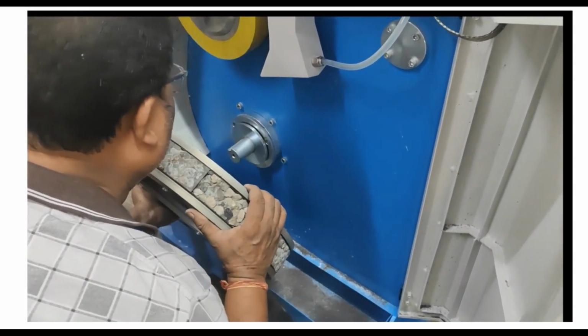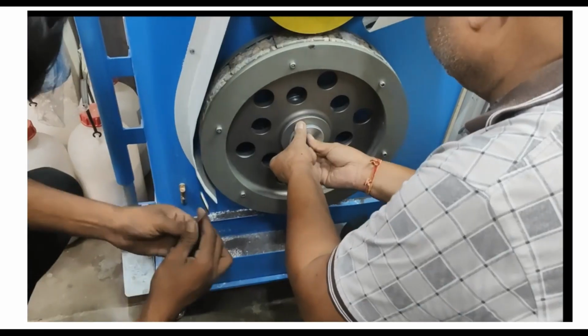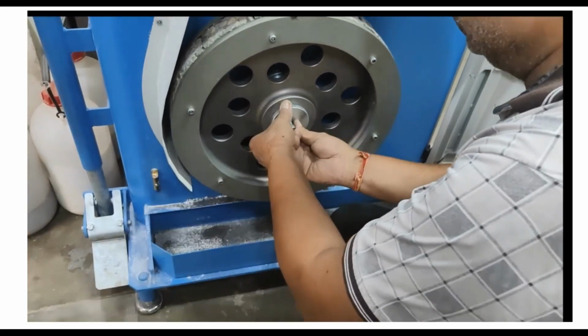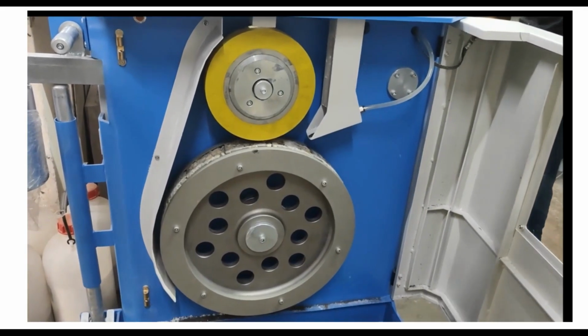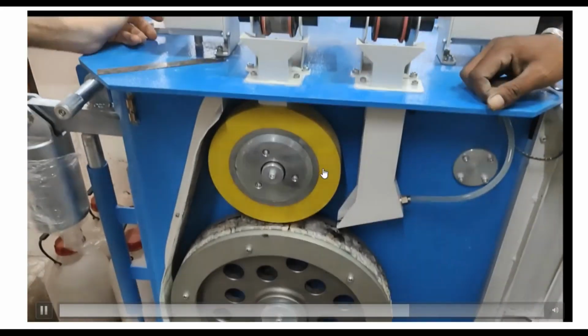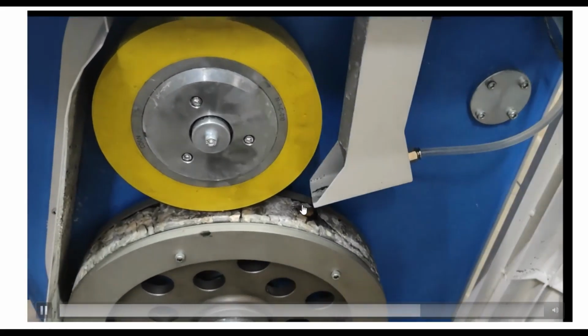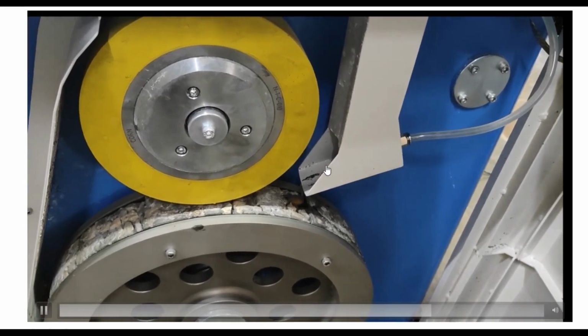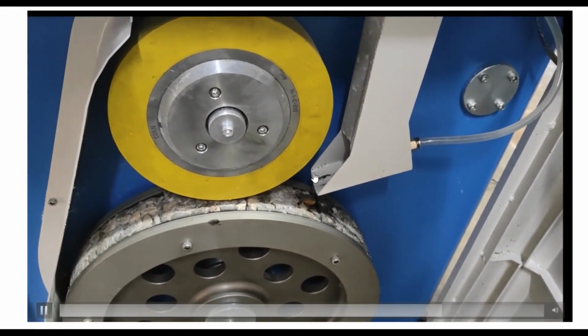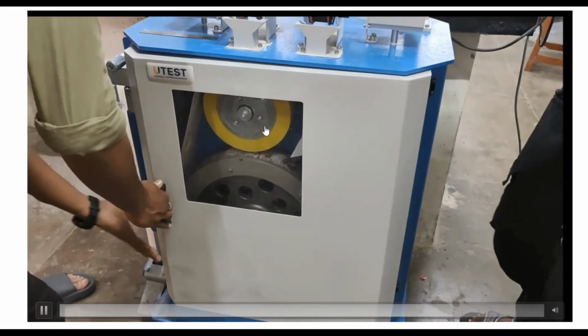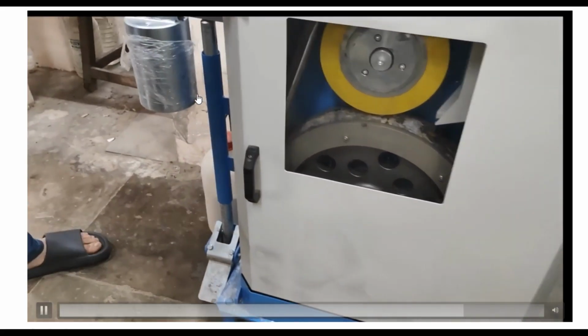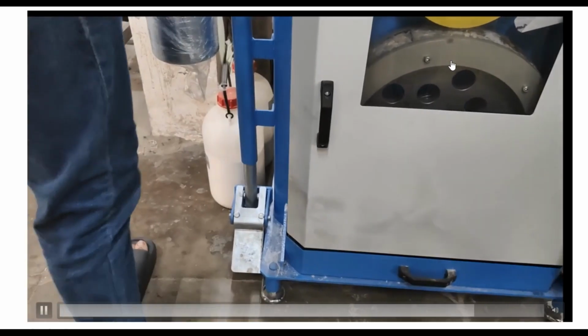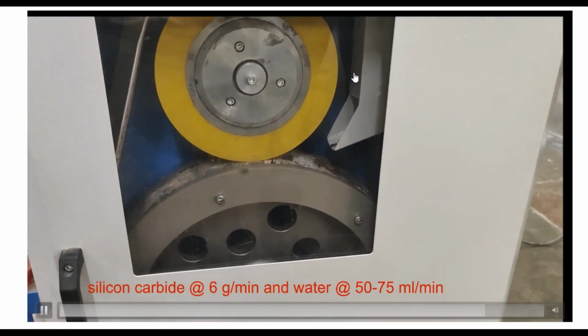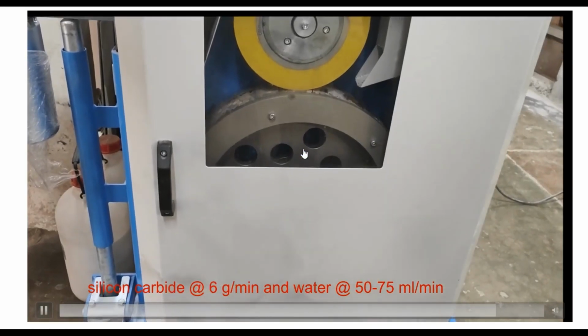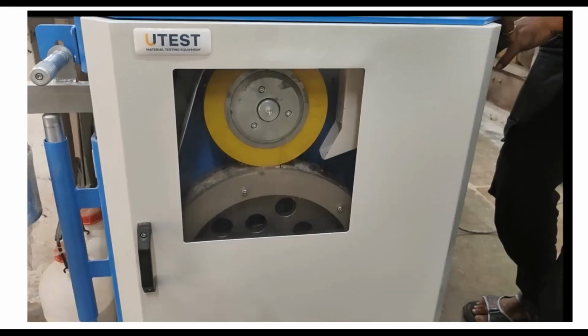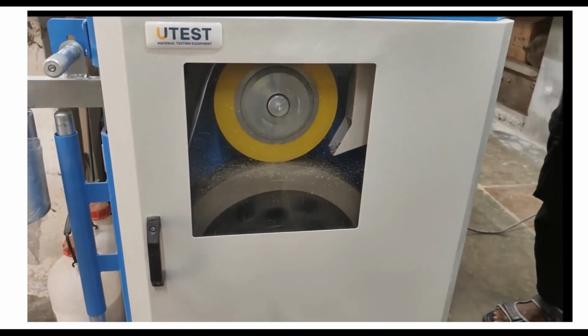Once it is done, then you fit the wheel back into the machine and close the door. Now we feed the silicon carbide plus water between the rod wheel and the pneumatic wheel. Close the door. Release the weight here so that this wheel, the small wheel, applies a load of 40 kg. Then rotate the machine at 320 revolutions per minute, and it is done for 3 hours.